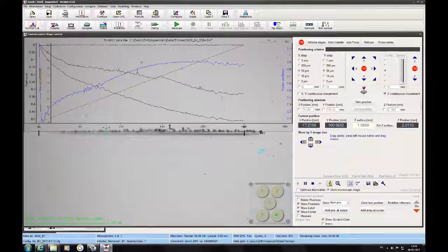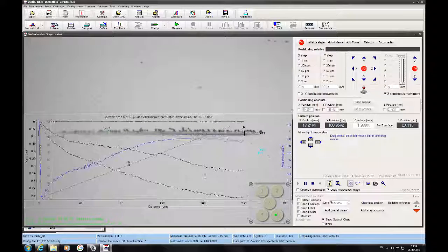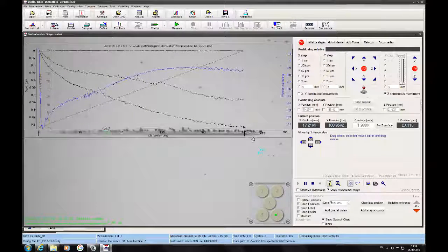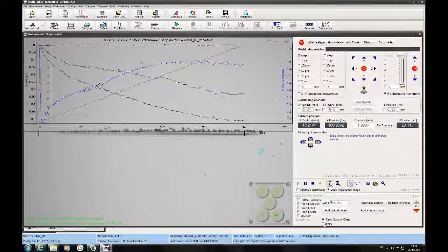You see the scratch. So the indications give you the begin, it's here, and the end of the scratch, and this is the additional range outside the scratch length where the force is reduced to 0, and this is also the range where the scan was done. The newest feature is that we can also insert a graph where you see the curves in the scratch and you can directly compare this with the scratch track in the optics. So, of course, if you don't see that, we can invert the colors, or we can measure here in the graph which force was at which position.